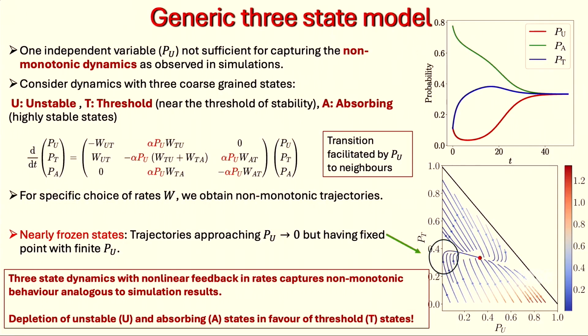Then I can write the corresponding dynamical equations, and when you look at the behavior that emerges, you find this very interesting behavior where, if I look at the population of unstable states and the absorbing states, with the number of cycles both of them actually diminish, and the population of the threshold states, on the other hand, goes up. So you have stable and unstable states, both of them converge towards the boundary.